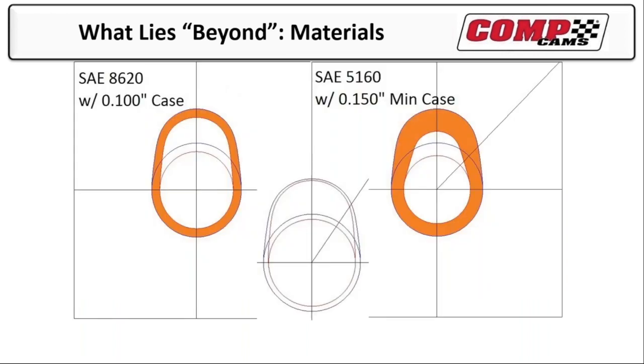And you can see this with this picture of the theory of it. 8620 is going to be the same depth all the way around. Any place that doesn't have copper, the carbon's going to diffuse into the surface, and you're going to get the type of profile you see on the left. With induction hardening, you're going to see more of that profile like you see on the right. I think it really gives a lot more flexibility.